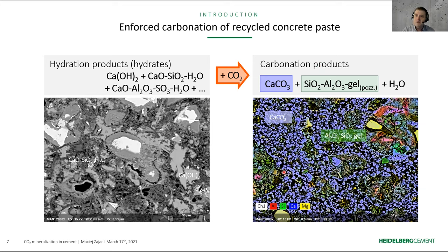The carbonation of the cement paste is associated with a characteristic evolution of the product's morphology. On the left-hand side, you see a typical backscatter electron image of the cement paste, which is partially hydrated, with all the hydrates and unreacted cement grains. And after the carbonation, a wet carbonation process, it looks like this. This is a pressed tablet, again a backscatter electron image of such a paste. You see these bluish or violet points; this is calcium carbonate. What happens during carbonation is that we are leaching calcium out of the original cement paste particles into the solution, where it precipitates as calcium carbonate.